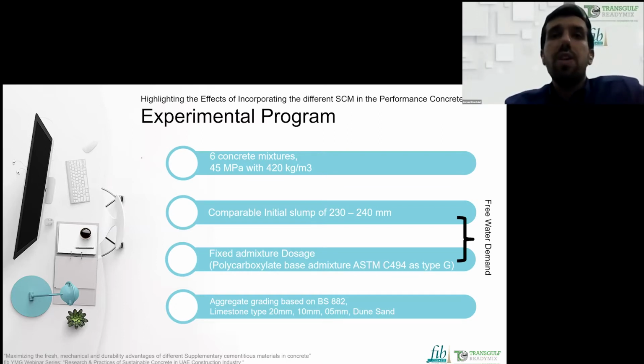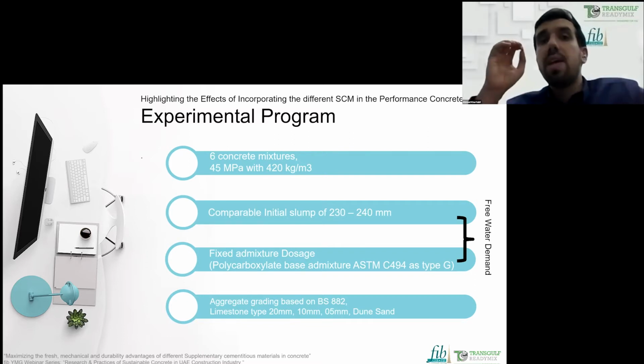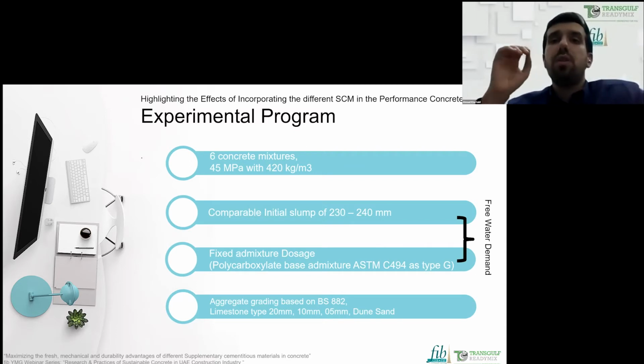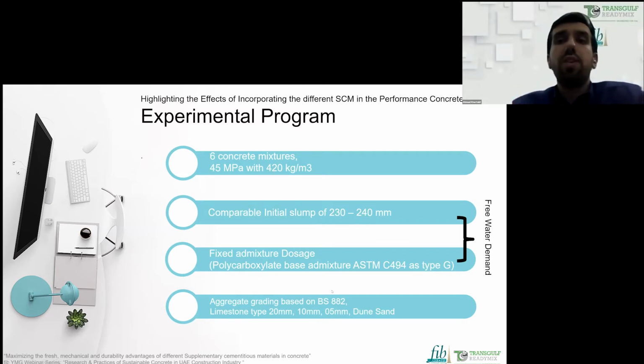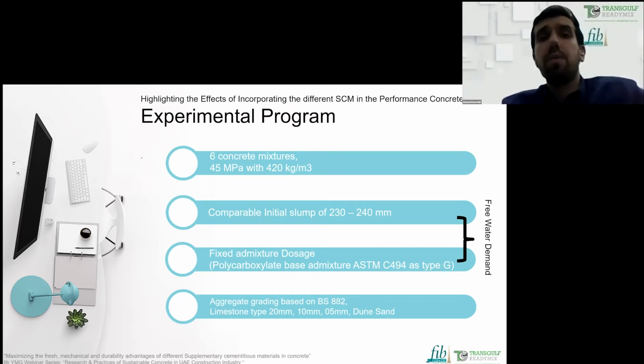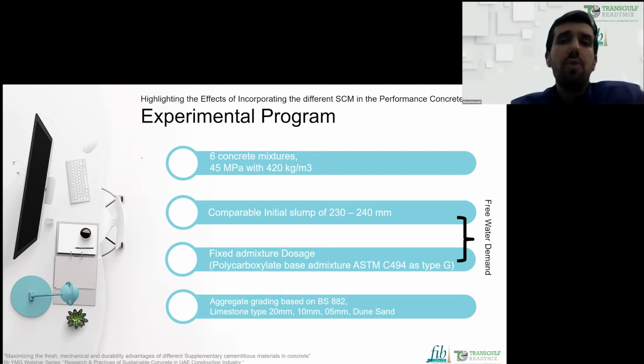So here in this study, actually, we wanted to maximize the benefit by also determining the minimum required free water to have an initial slump of between 230 and 240. But we fixed the cement content to exactly 420, and the admixture dosage was fixed for all the concrete mixes, in reference to the control mix, which is 100% Portland cement. The aggregate type used in this study is limestone, which is common and available here in the UAE, graded to BS 882, and combined grading also. The maximum aggregate size was 20 mm.